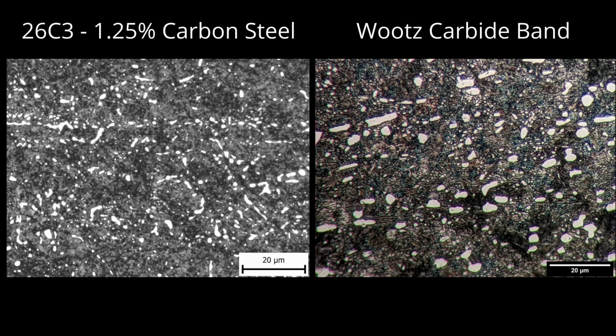So here is the microstructure of Spencer's Wootz. This is oil quench. There's a little bit of pearlite in there. We're looking within a carbide band. These carbides are bigger than the carbides in 26C3. Those bigger carbides reduce toughness. Of course, its edge retention is better, the Wootz's. But I think overall, we can make better steel today than we could back then.